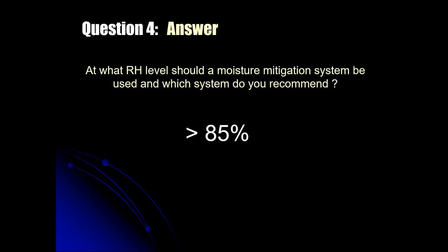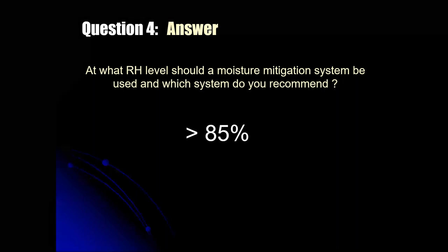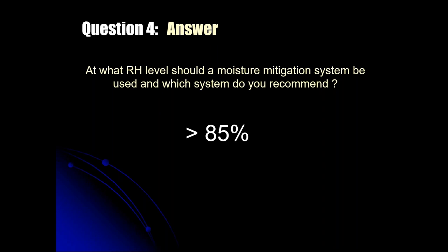Now, some of you may remember when we first adopted relative humidity testing in this country, in our document ASTM F710, which is the standard practice for preparing concrete subfloors to receive resilient flooring, we showed a table that showed, in absence of a manufacturer's stated value, 75%. Well, 75% was put in there because everyone knew or believed that we wouldn't have a problem at 75%, and I truly believe that. But I had the privilege of overseeing studies on the in-situ test method at the Grace Laboratories outside of Boston back in 2009 and 2010.